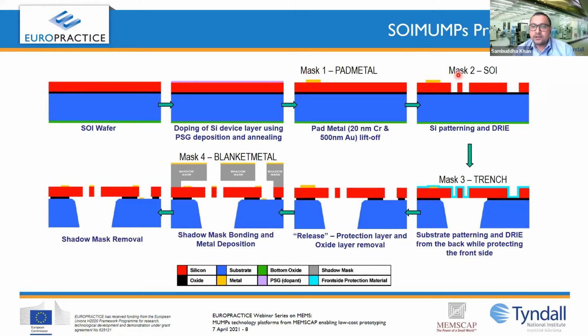Then the wafer goes into the first level of etching process, for which the mask called SOI is used. In that, the actual device is patterned on the top silicon layer, and then comes the backside etching. For that, you need to flip the wafer, so there is a chance that the silicon layer can be damaged. That's why a top protective layer is deposited on it, and then it is flipped and the substrate is patterned. Through DRIE, deep reactive ion etching, the substrate is etched using the mask called trench.